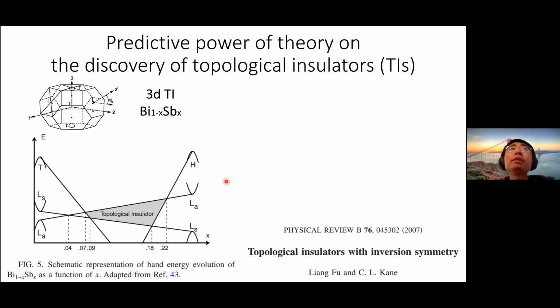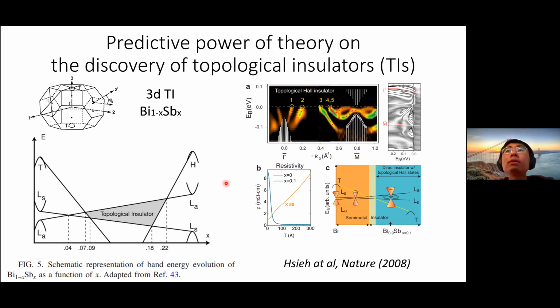After that theory prediction, experimentally, people found that if you look at the surface of this bismuth antimony, you can identify there are actually 5 crossings between the surface bands and zero energy. This is an odd number, characterizing that the system has a non-trivial Z2 index — in other words, there are an odd number of Dirac fermions on the surface of this material.